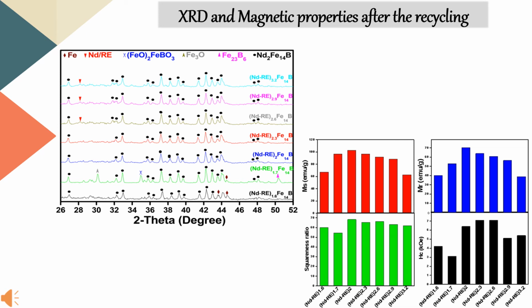If we talk about the XRD, where there is not enough Nd or Re, like in the case of NdRe1.6 or NdRe1.7, the good phase was not obtained and there are a lot of impurities in the product. But when we added much more extra Nd, we also got some extra Nd phase. So from this composition we were able to optimize a good product with ideal magnetic properties and ideal structure.